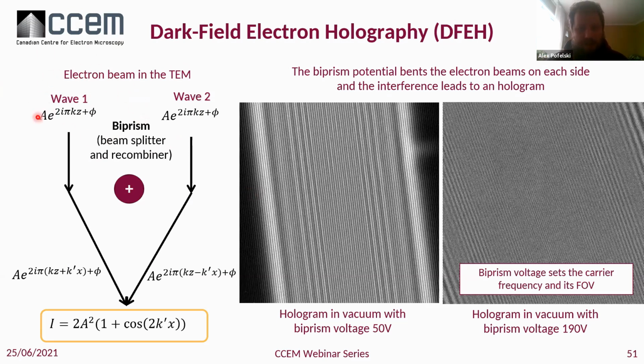So this is just an example here, that you take the wave going into vacuum and another wave going into vacuum, so just your electron beam. You put in between something that you call the biprism, that is acting as a beam splitter and recombiner just underneath. So by recombining, you can think about just having a positively charged wire that is bending the K vectors of this electron beam on each side. And this bending, this difference of bending, you can see here, and this just changing the size of the lateral component, is just then after when you do the mathematical equation, going to bring this oscillatory component. And that's why you see those types of holograms in vacuum. That's what is possible to see by bringing this biprism in between.